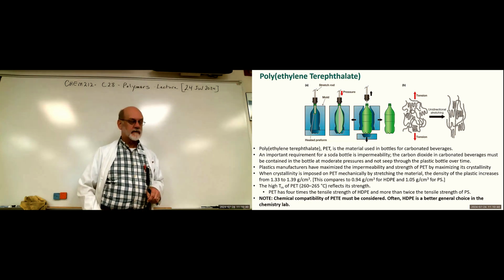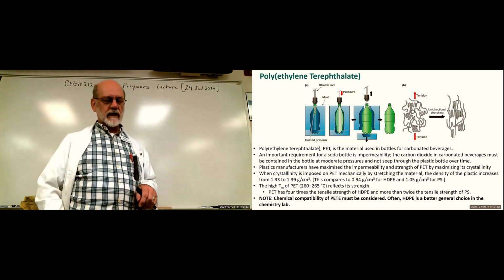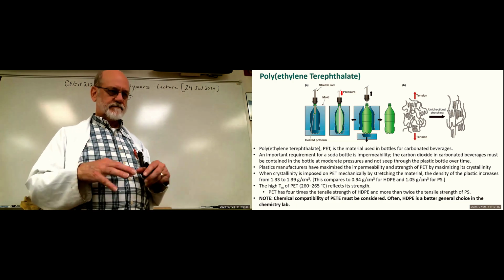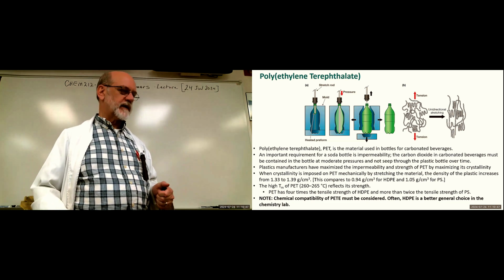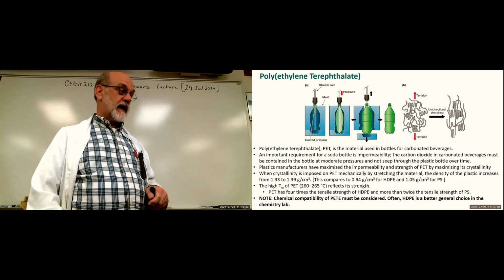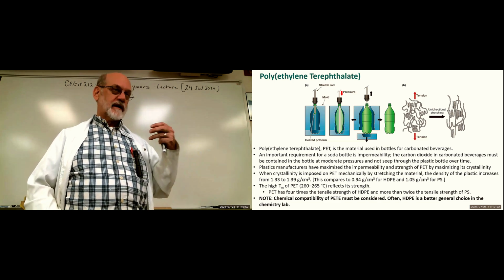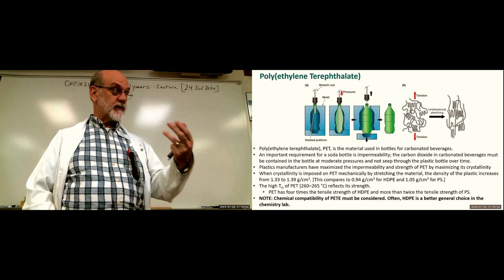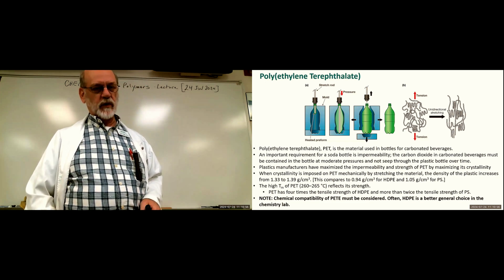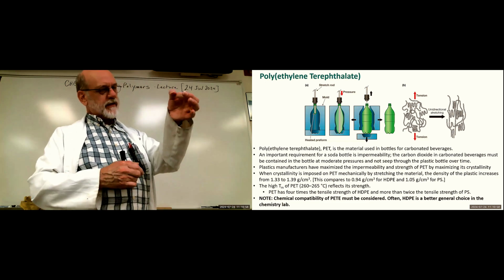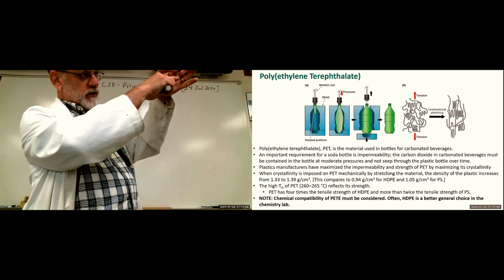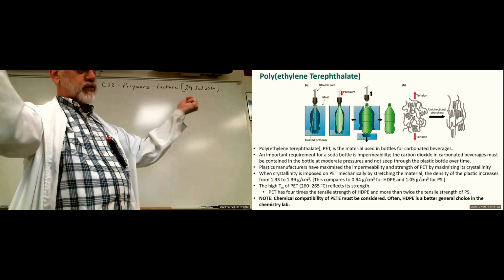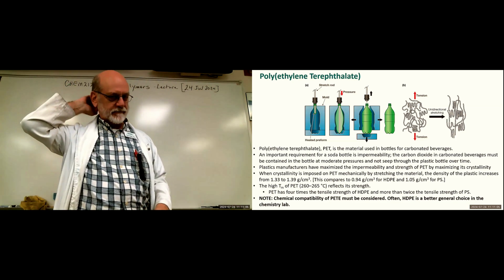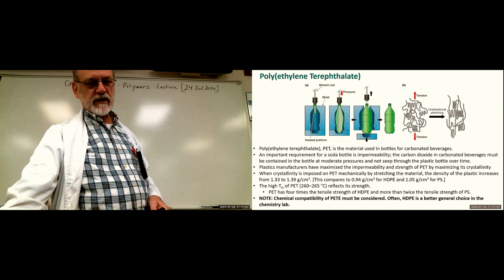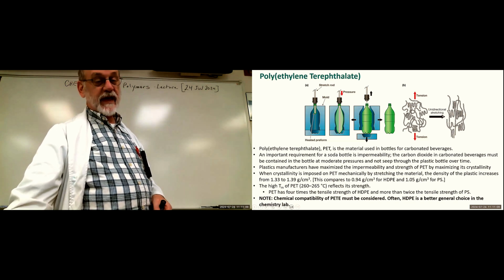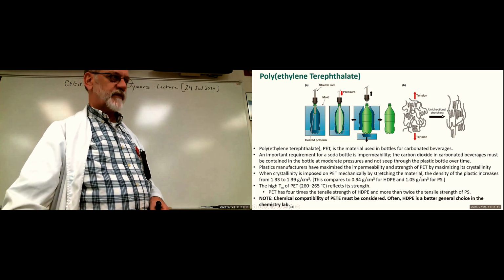And we only do it once because you get stress cracks eventually. I had one blow up. I didn't learn my lesson. I'd used a bottle several times in the same experiment, and one of them blew up right at the cap right here. There must be more strain there than anywhere else, and it sounded like a gun. Fortunately, nobody was injured. But after that, we use them once, cut them up, throw them away.